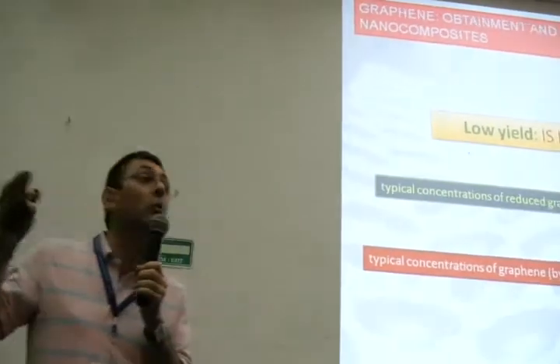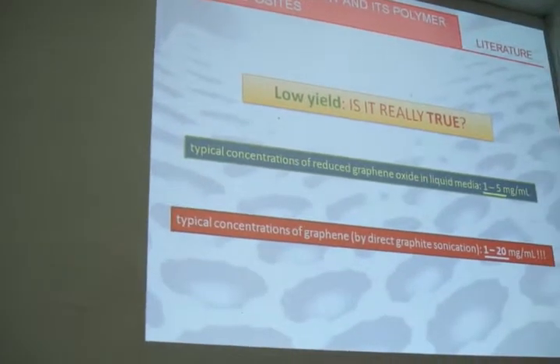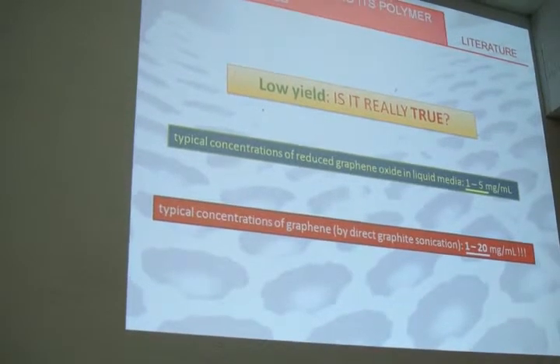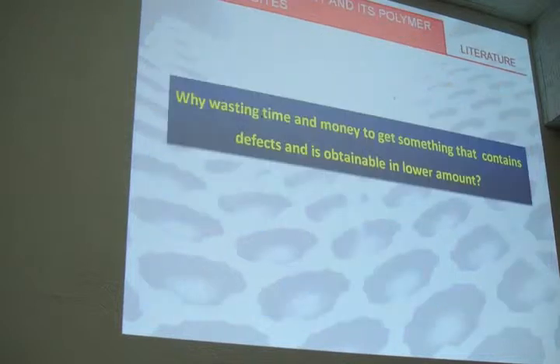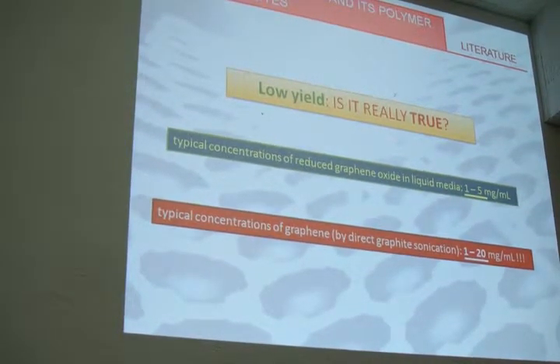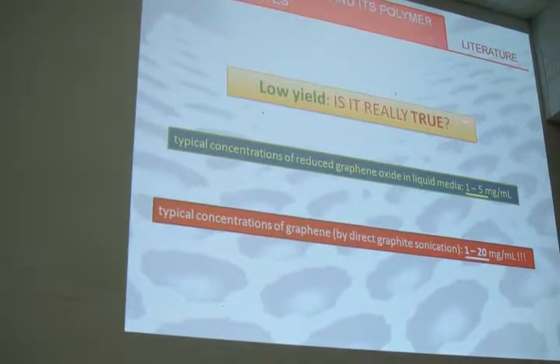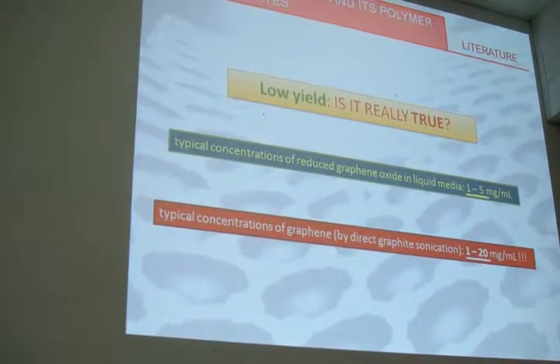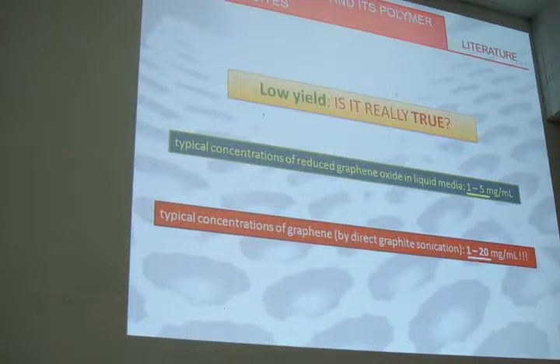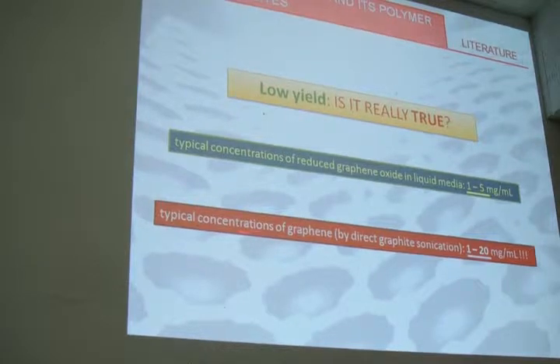At the beginning, the first paper published by Coleman was about a concentration of about 0.1 milligram per milliliter of graphene. Low yield. Yes. The first paper. At present, typical concentrations of reduced graphene oxide or its more or less oxidized derivatives are in this range, 1 to 5 milligram per milliliter. But if you use the easier method, without any chemical manipulation, you are in this range, 1 to 20 milligram per milliliter, which are the highest concentrations of graphene in liquid. So, low yield is not true.